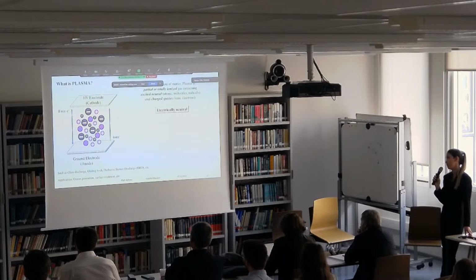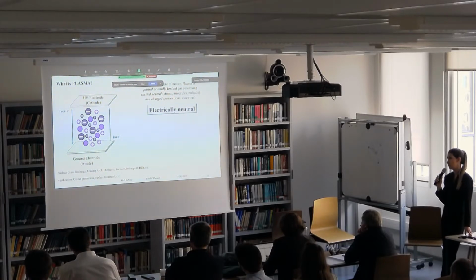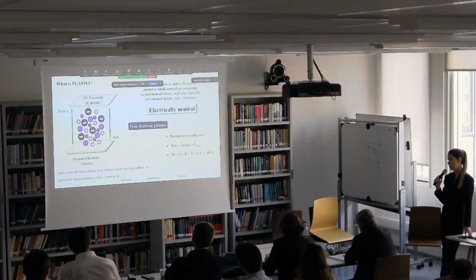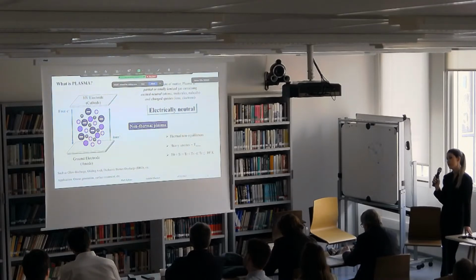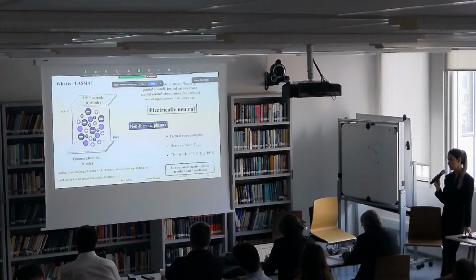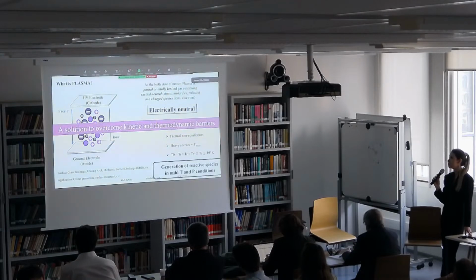Plasma, as the fourth state of matter, is a partially or totally ionized gas, including excited neutral and charged species, which are electrically neutral. Plasma can be produced between a high voltage electrode and a ground one by applying an electric field. While the excitation happens near the high voltage electrode, the ionization takes place near the ground electrode, and by this means, plasma is produced. In general, plasma can be divided into two types, non-thermal and thermal plasma, and in this work we are going to use the DBD plasma, which is non-thermal, thermally non-equilibrium, and can be operated at atmospheric pressure and low temperature. And by this, plasma can be a solution to overcome the kinetics and thermodynamic barriers.